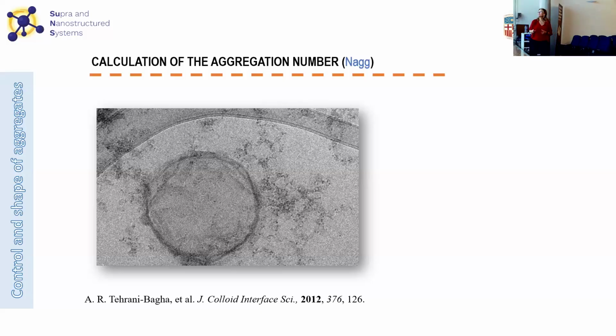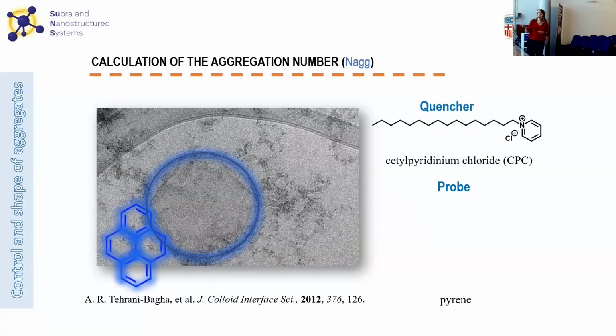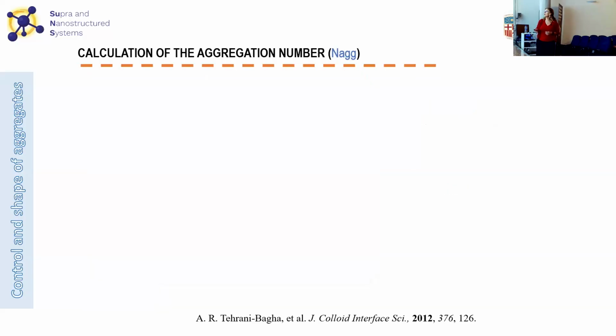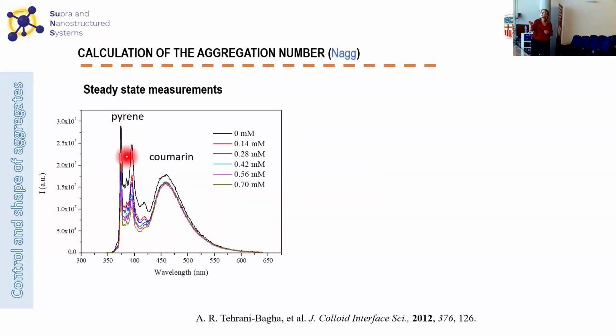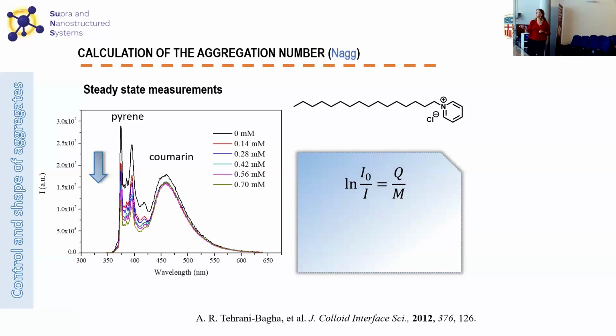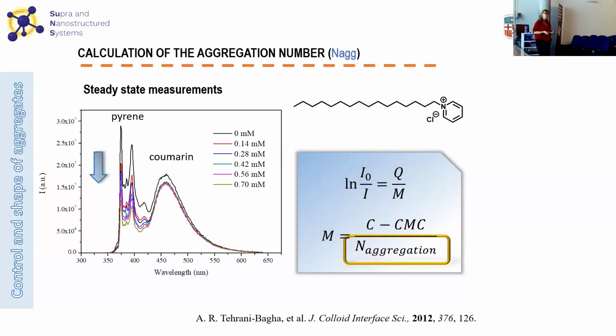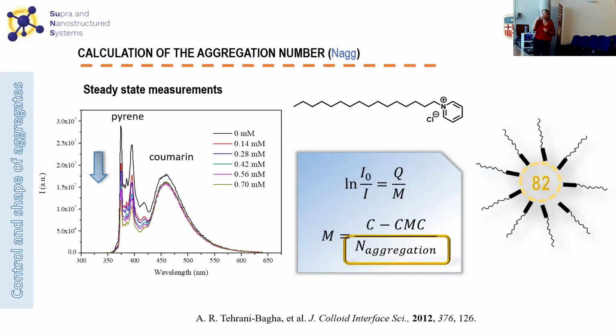Okay, so the procedure is just trying to stain our sample, the aggregates. We used pyrene, and our samples can be stained in a blue color, let's say, as presented here, and then introduce increasing amounts of a quencher, this one, the CPC, making the emission of the compound decrease in intensity. So what we have to plot is how the emission of the pyrene is decreasing in intensity, but not the emission of the coumarin. So the molecule is stable, the pi-pi stacking is stable, but it is just the probe that is being quenched. And this can be directly correlated by this equation, the difference in the intensities, and from here we can calculate the number of molecules that are present in the aggregates. That in our case was around 80 molecules in our sample, so it was quite big.